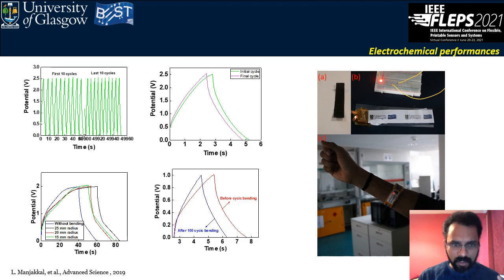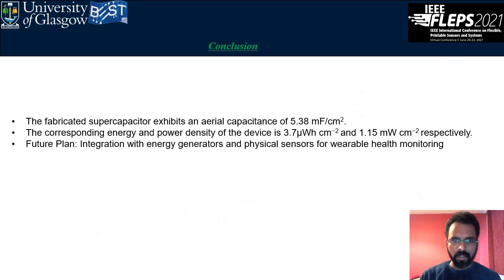And we also characterized it without bending and with bending. Different bending radii have influence on the supercapacitor, and here you can see the cyclic bending performance of the device as well. Finally, we applied this device as a wristband supercapacitor to power an LED. This device shows an areal capacitance of 5.38 millifarad per centimeter square, an energy density of 3.7 microwatt-hour per centimeter square, and a power density of 1.15 milliwatt per centimeter square.